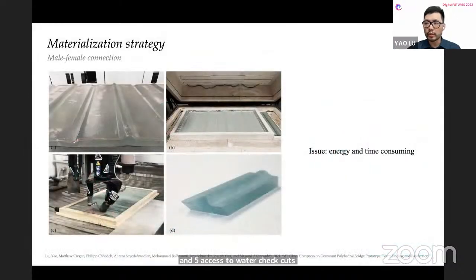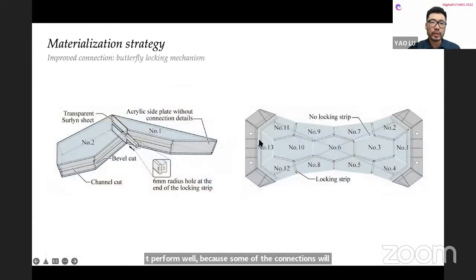There are several issues that we have found through this testing process. First of all, the whole casting process is very energy and time consuming. And more importantly, it doesn't perform well because some of the connections will open up under asymmetrical loading conditions. And therefore, we shifted to another improved connection detail called butterfly locking mechanism, which is also what we used for